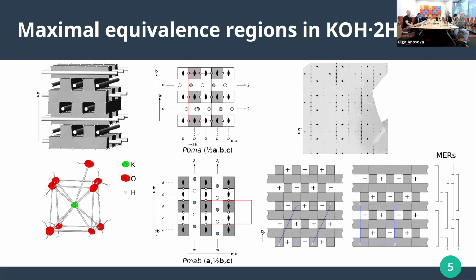And what you see is that these hydroxides are moved either to the right or to the left. And then the next layer is rotated by 90 degrees, and the next one again by 90 degrees. So here the hydroxides go in the other direction. And again, you can move them up or down. And the crucial point is that they have different lattices in these two layers. And when you apply OD theory, there's a whole bunch of theory, that tells you that you can combine these layers, but basically you can choose how these hydroxides are located, either in one direction or the other direction.